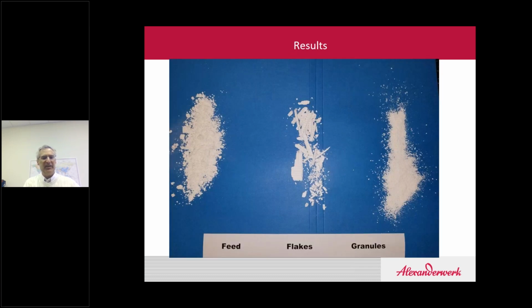Taking a look at the results, if you look at the feed material, which is on the left-hand side of the screen, you can see it really looked like a very poor flowing product. I believe this was the 40% APAP I took a picture of here. Material did not want to flow. The flakes that we generated, and this is the sample coming out after the flake crusher, was a typical flake that you see. Each one of them was about 1.4 millimeters thick. And after the material ran through the RFGs, we were able to produce nice flowing granules that you see on the right-hand side.